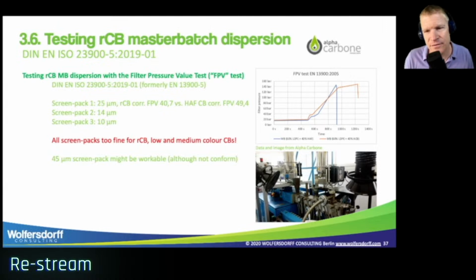Interestingly, if the filter pressure value is corrected, the recovered carbon black actually performs better than the normal carbon black. So I hope that we can repeat that test and do the full processing of, I think, 200 grams master batch again with those two carbon blacks, because I think actually that Alpha Carbon recovered carbon black has pretty good dispersibility.